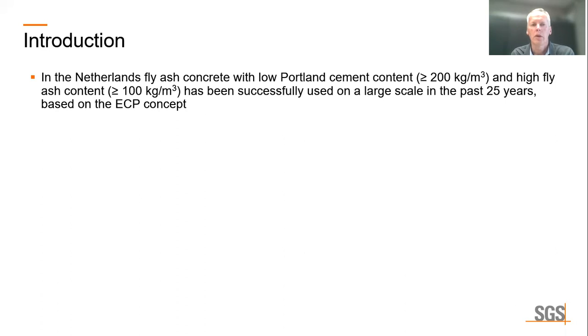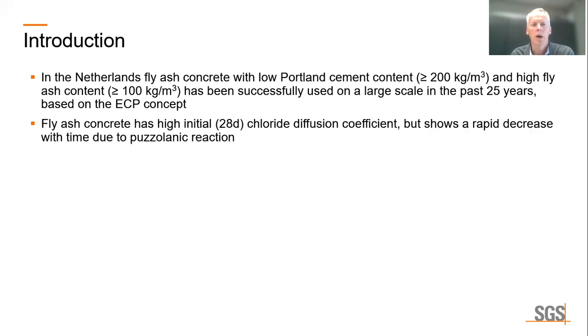In the Netherlands, we have used fly ash concrete with low Portland cement content and high fly ash content successfully on a large scale in the past 25 years, based on the equivalent concrete performance concept. However, it is well known that fly ash concrete has a high initial chloride diffusion coefficient, but shows a rapid decrease with time due to the pozzolanic reaction.